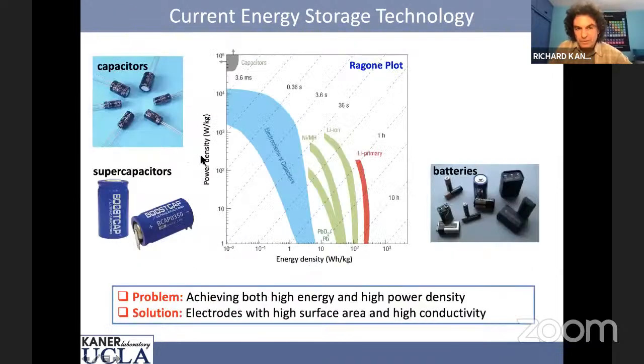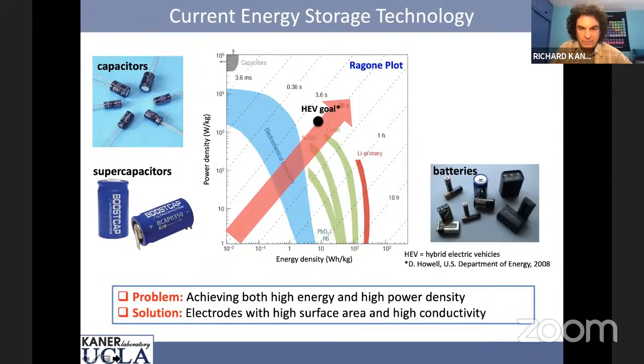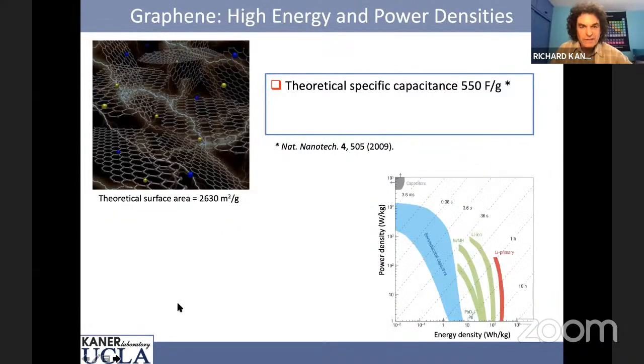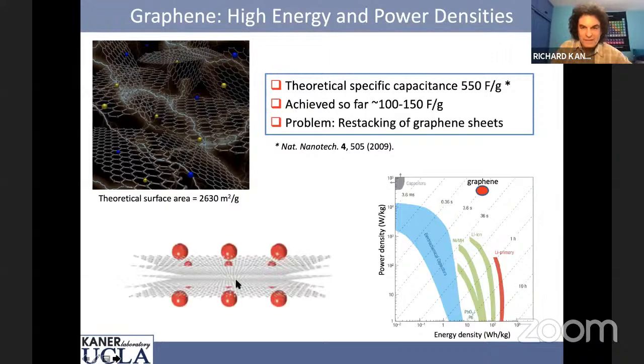Here's a Ragone plot, which is power density in watts per kilogram versus energy density in watt hours per kilogram. And what one wants to do is achieve both high power and high energy. And this is the goal for the US Department of Transportation for electric vehicles. And what's interesting is graphene by itself, in theory, with a capacitance of 550 farads per gram, could solve this problem. So here's graphene on this chart. Now, the problem is when you actually go and try to make a device out of graphene, you don't get 550 farads per gram. You only get about 100 to 150 farads per gram.